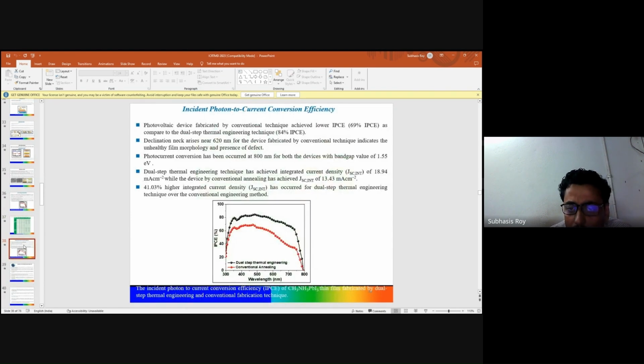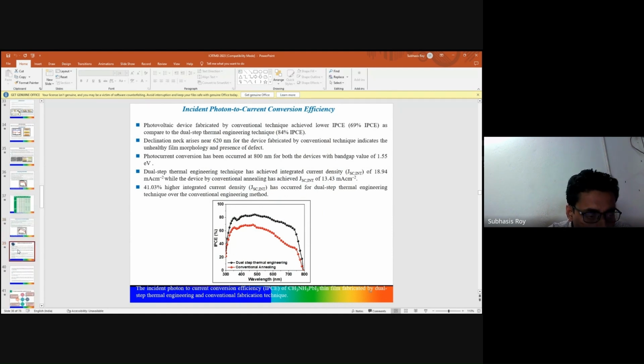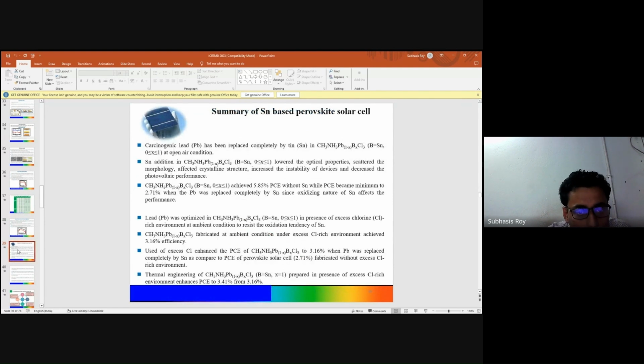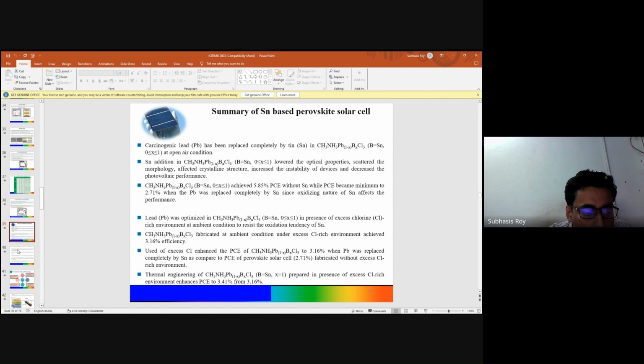Then if you see the IPCE, it is giving an 84% IPCE value in the case of the dual-stage thermal engineering process. So here we can conclude that in the Sn-based perovskite solar cells, we optimized the performance of the Sn-based solar cells for replacing the lead with Sn, and we did the performance analysis of the solar cells.